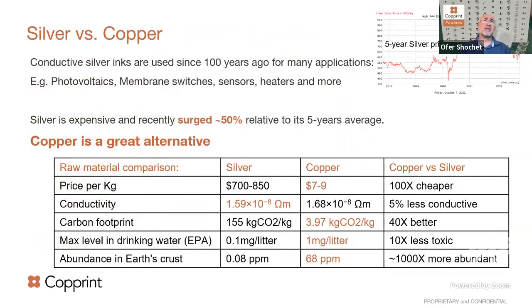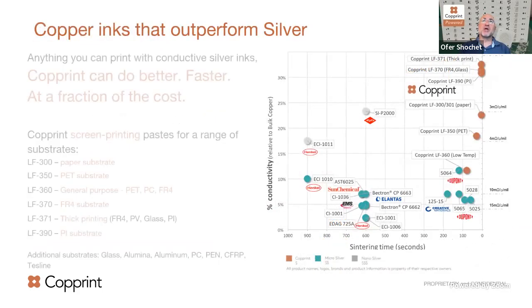And also the comparison between silver and copper is very simplistic. Silver as a raw material is about 100 times more expensive than copper. The conductivity of silver is about 5% better than copper, but all other parameters like carbon footprint, like toxicity to water, like abundance, copper wins very, very easily. And therefore the interest to move to copper.